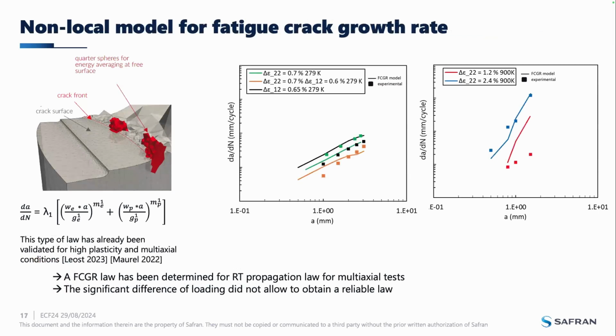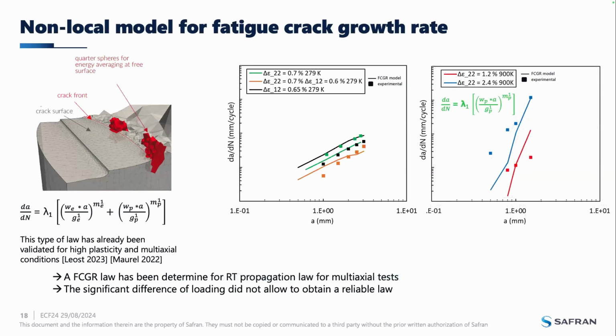So based on my experimental results, I have been able to try to determine a propagation law for a multiaxial test. So here in green, you have a pure tensile test, in black, a pure torsional test, and in orange, a mixed tensile and torsional test. You can see that it's relevant, but for the moment, it is not perfect. And I also tried to do this for the experimental tests at 900 Kelvin. But because of the significant difference of loading, I don't obtain a reliable law. I tried to take into account only the plastic energy, but it is not sufficient.